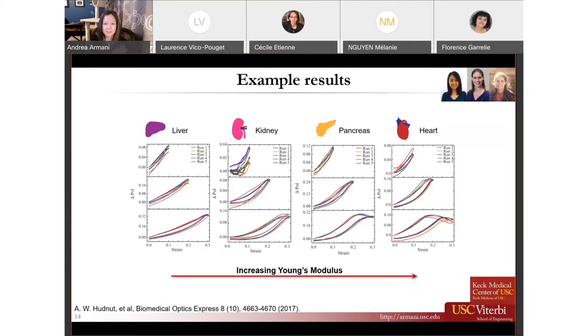I'm going to focus mainly on some of our cartilage data, but just as an example, here are four different organs, going from liver, kidney, pancreas to heart. If you look at different strain rates, you can see that the viscoelastic response clearly changes as you increase the strain rate. A very common viscoelastic material that people are familiar with is gelatin. If you think about how fast you compress gelatin, it will have a very different response. And tissue is the same way.